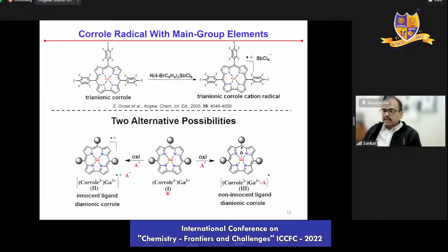So the two possibilities that can happen are: you take gallium now instead of copper, oxidize it, and you get this same cation radical, and you oxidize it adding an anion. What is supposed to happen is, if the metal is going to get oxidized, then you are going to have an anion bound on the metal. So that is going to say whether this ligand is innocent or non-innocent.